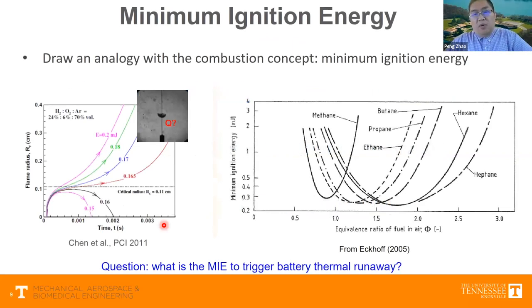So one of the most important concepts to evaluate a reacting mixture is the minimum ignition energy. Basically it describes the amount of energy needed for a hotspot or a spark to trigger a self-sustained flame in a reacting mixture. As you can see, for this rich hydrogen-oxygen mixture, when you have ignition energy above a certain critical value, you can have successful triggering of the flame. So the question is now, in case there is a hot spot induced by local heating or internal short circuit, what will be the minimum ignition energy for that hot spot to trigger thermal runaway?